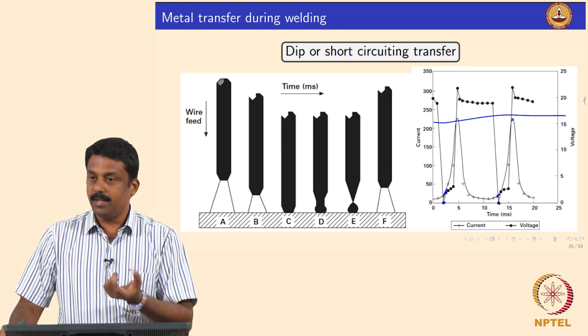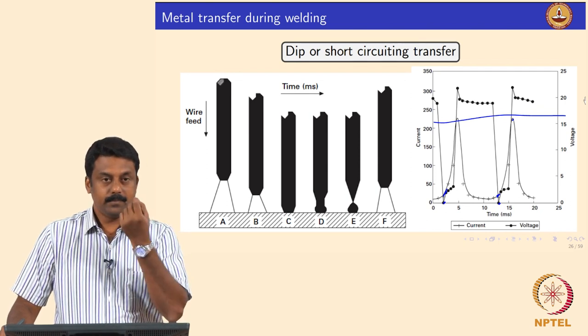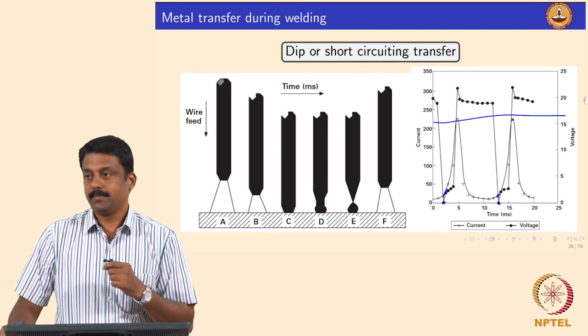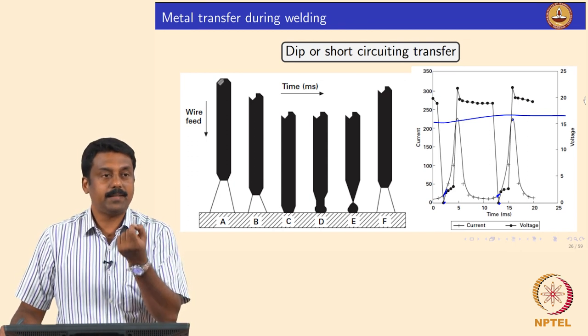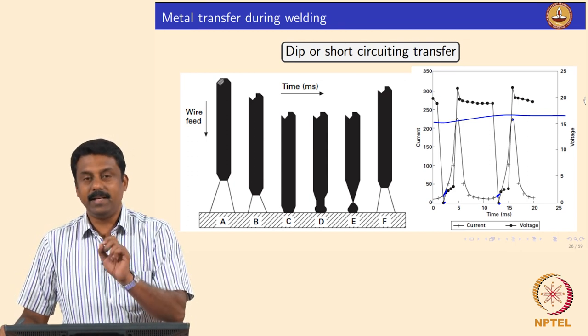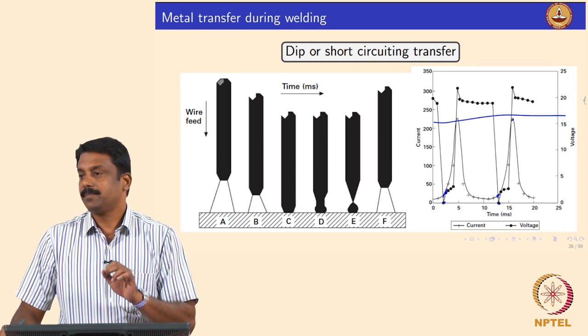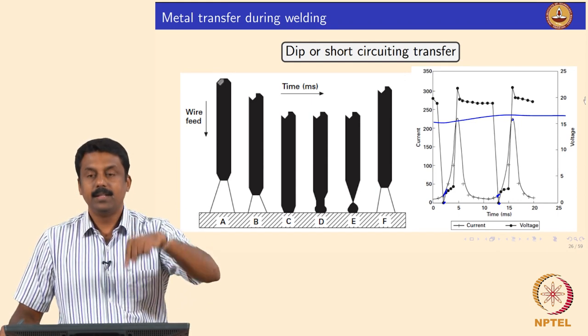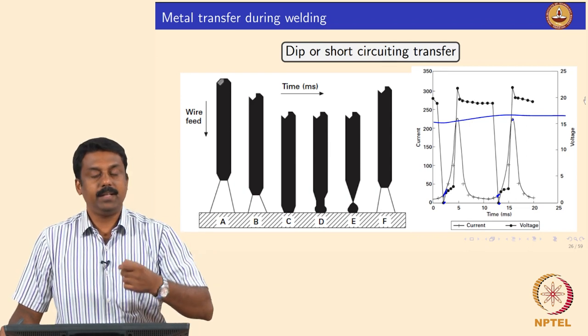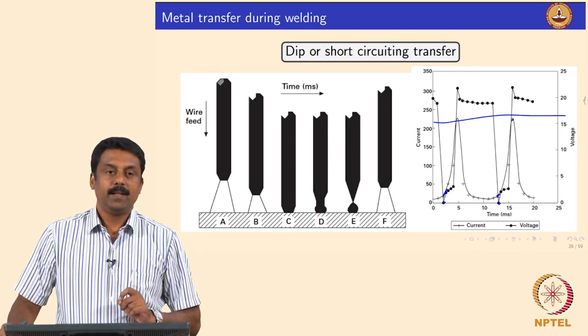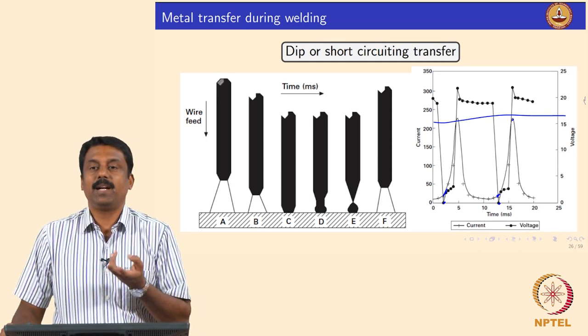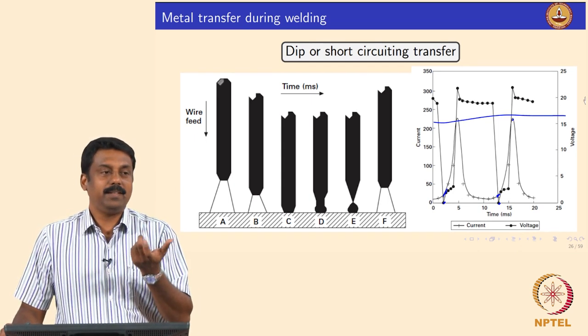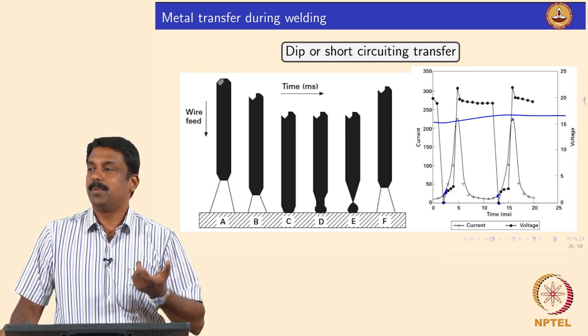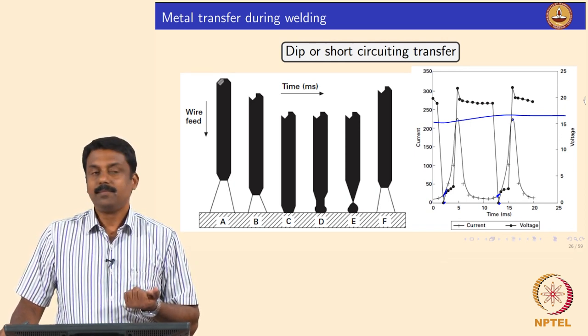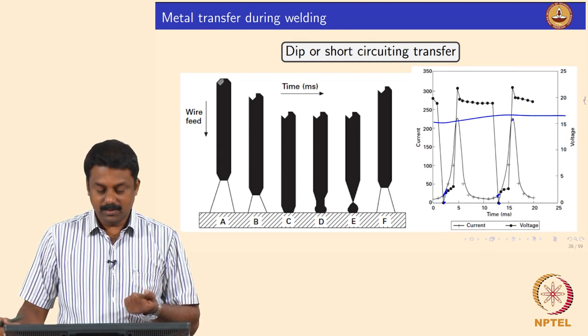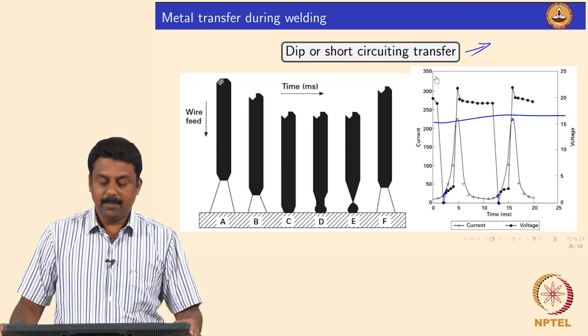Whereas in the short circuiting transfer, when the droplet is transferred, we also switch off the current. So when the droplet is transferred, you transfer it close to the melting point of the droplet, okay. So the way you are dipping it, the droplet temperature and melting temperature become more or less the same. That is why this process is also known as cold metal transfer, because the droplet temperature is much, much lower than in a conventional droplet transfer. Yes, it is clear. So this is known as controlled dip short circuiting transfer.